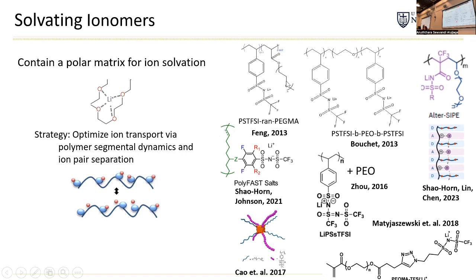And so how these polymers are designed is that they all have some polar part, usually this polyethylene oxide or polyethylene glycol part. And then they have these tethered anions. And you can see that these anions are really big, so there are a lot of atoms. And that's very, very important, because the anion being large and having many atoms means that the electron is highly delocalized over many atoms. And so the binding energy between the anion and the lithium is smaller. Therefore, it's easier for the polar polymer chains to totally solvate the cation and separate it from the anion.